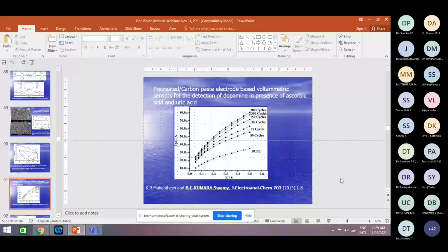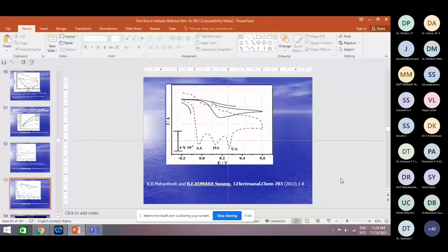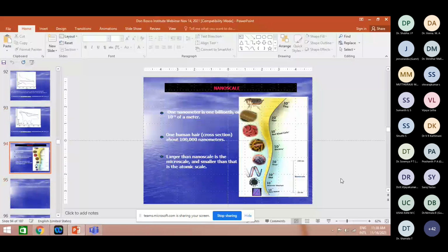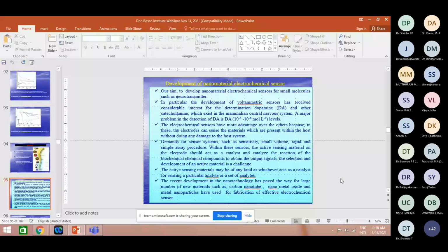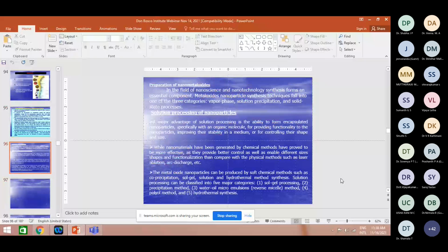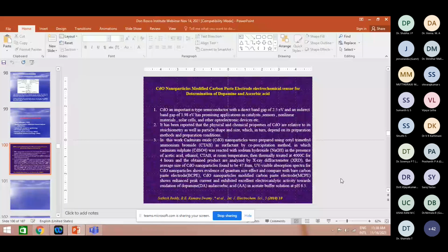I was amazed, because when you take a bare carbon-based electrode, we got one oxidation peak. But after pre-treatment, we got 3 peaks for ascorbic acid, dopamine and uric acid with very high sensitivity, because you see so much difference in the peak potential and such a large increase in the peak currents. Then, in nanochemistry, we also developed some nanometal oxides. With one of my students, we prepared cadmium oxide nanoparticles. And for this cadmium oxide nanoparticle paper alone, we are the first in the world.